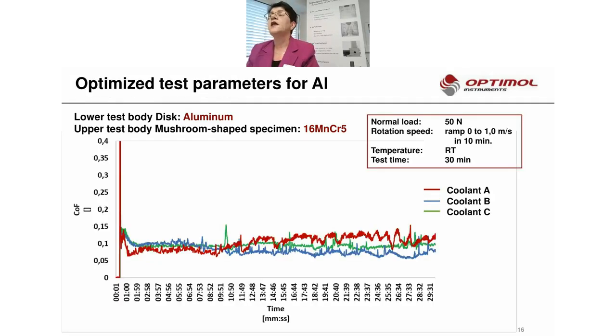And we have done it recently, and we could see that in this case, even though we also reduced the normal load, we can have a good differentiation and could make a ranking also for aluminum as working material. And you can see that maybe coolant B would be better for aluminum. Of course, the user can say this differentiation is not enough for me. You can change your parameters easily. That is what you can really do very nicely with the SRV. You go to higher load, you change the temperature, or in this case, you change the velocity, and you can have differentiation.